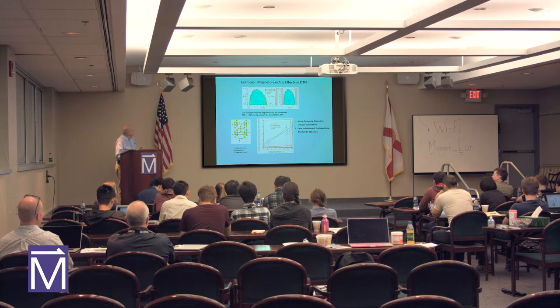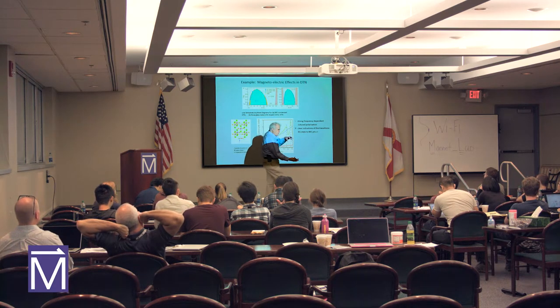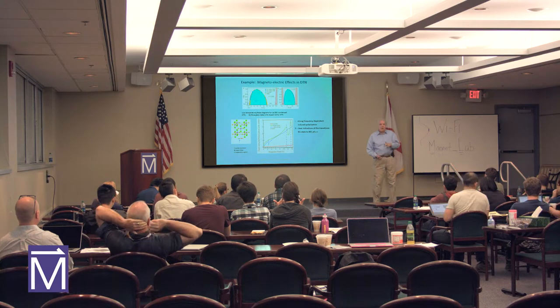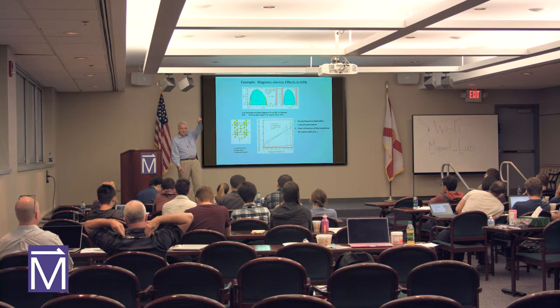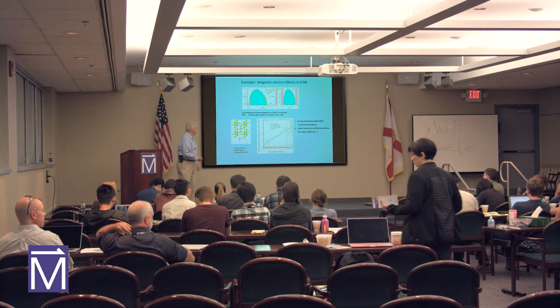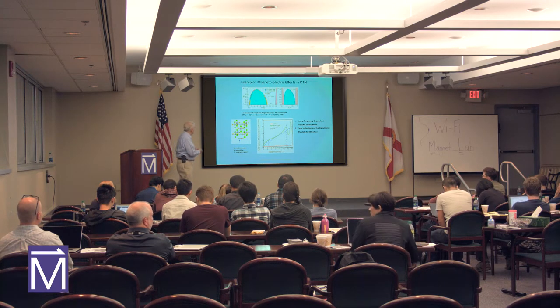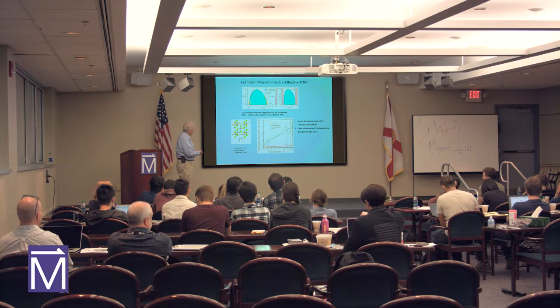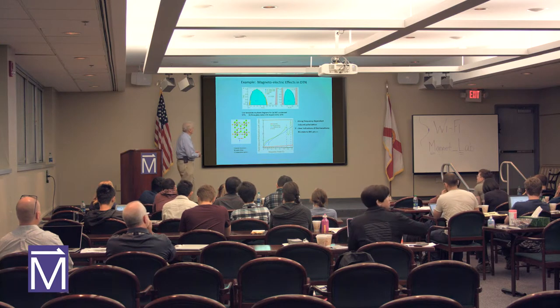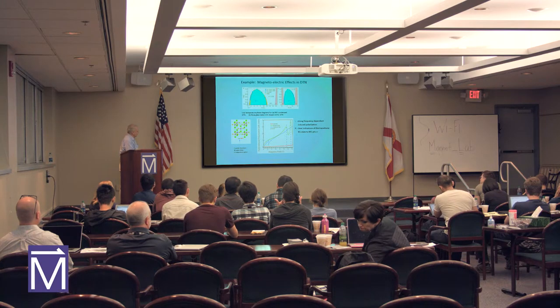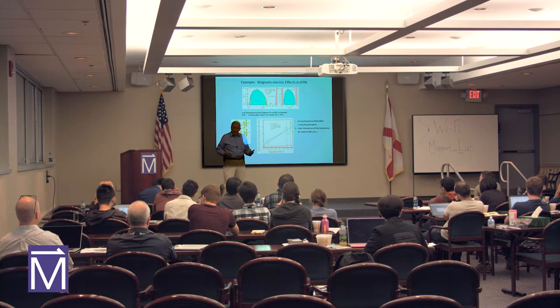In recent work, these same materials — the molecule that Vivian Zapf used was a thiourea compound, which has an electric dipole moment. So you have nickel spins connected via thiourea to another nickel spin, providing the magnetic interaction, but there's something polar inside. The idea was to see if we can change the magnetic moment by applying an electric field — and there was a huge effect. Measuring the polarization as you change the field, at the critical temperatures it splits into a doublet transition. There's a strong magnetoelectric effect. Partner compounds exist where these transitions occur not at millikelvin temperatures but at hundreds of kelvins, so there's opportunity to make interesting practical devices.